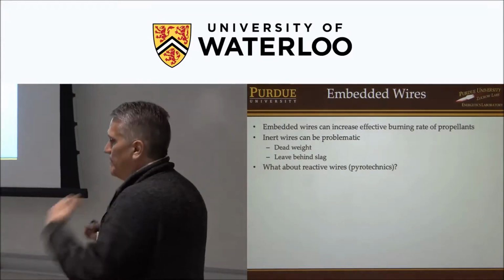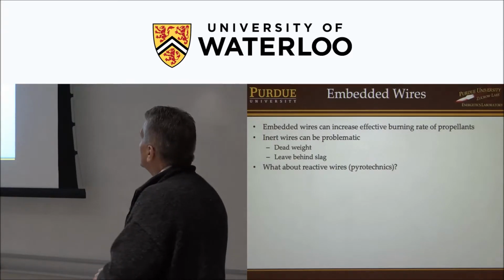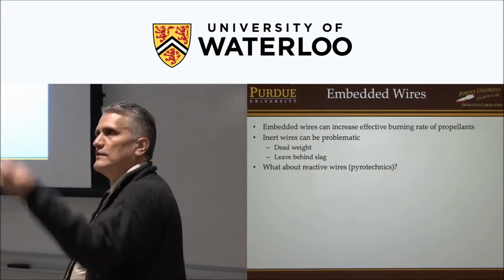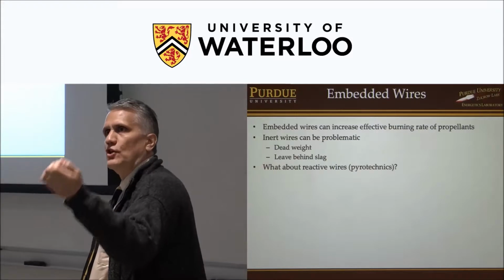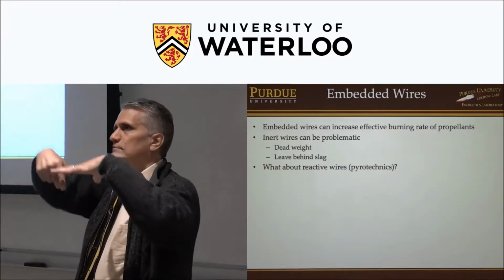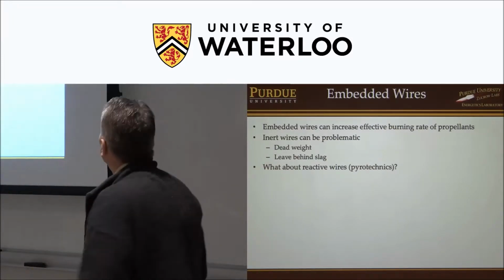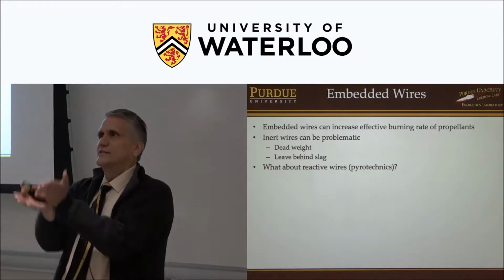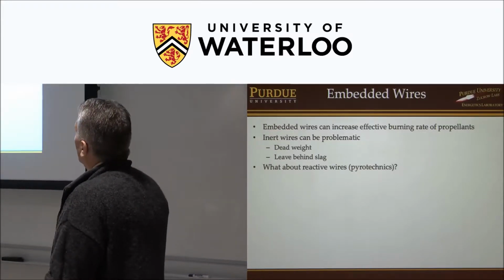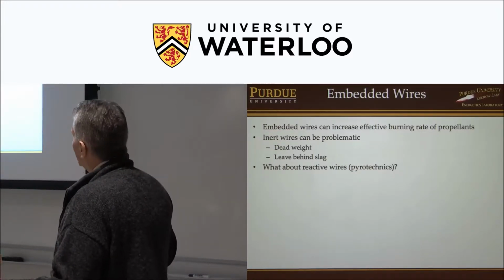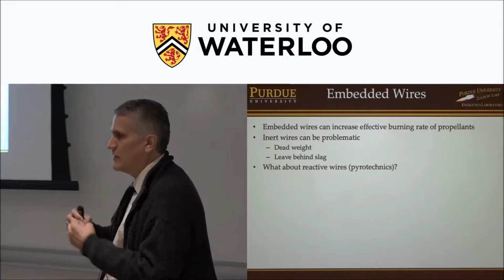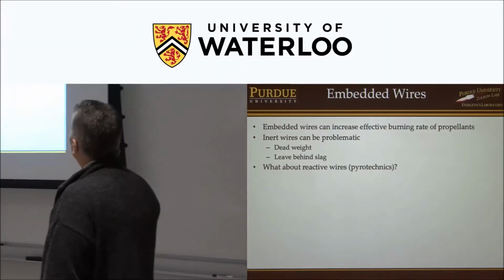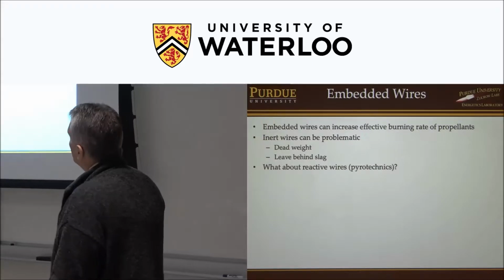And so embedded wires are sometimes used in solid propellants to increase the effective burning. They increase the heat conduction along those wires. So think of a propellant with some, could be copper, aluminum wires, whatever. And as that heat conduction is improved, it creates these kind of cones, these divots. The inert wires can be problematic though. There's dead weight. They leave slag behind. They have clunky products that go out through your nozzle. Could corrode your nozzle or erode your nozzle.